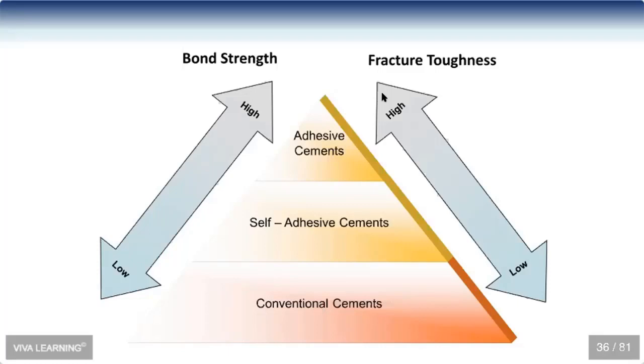And so increasing the fracture toughness of an Emax restoration, for example, can be improved by using one of these two cements, a self-adhesive or an adhesive cement. So that's one of the things to keep in mind. For example, I think that using something like Emax Prime on a first molar makes a lot of sense. I've got the 3Y strength of that zirconia at the margin and the 5Y in the occlusal third. And somebody might say, but I really like doing Emax on molars, the lithium disilicate version of it. And that's fine, provided that you can reduce enough occlusally. But then I would suggest that you definitely adhesively bond that Emax crown into place on that first molar.